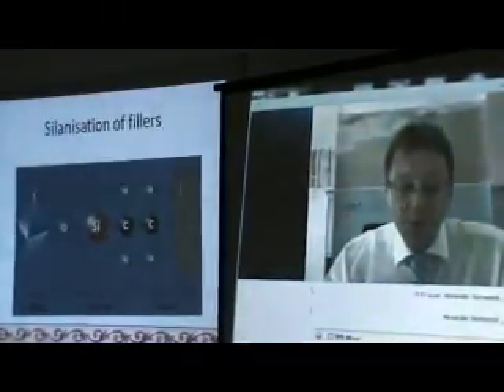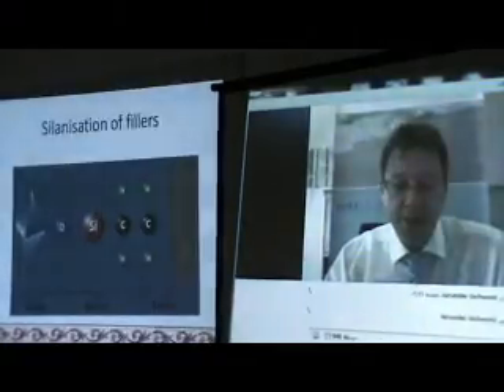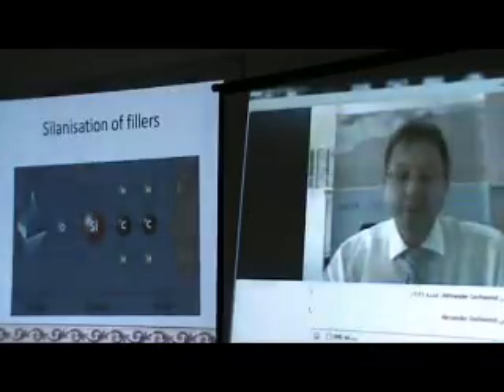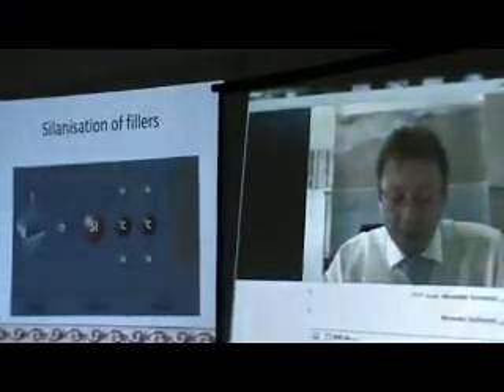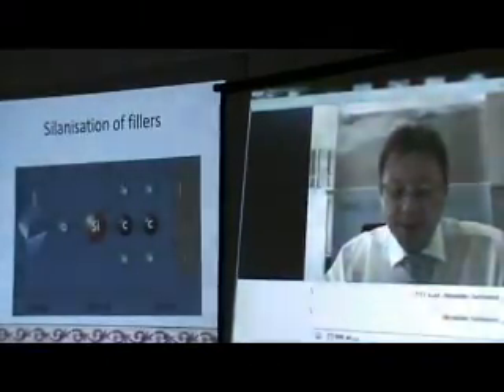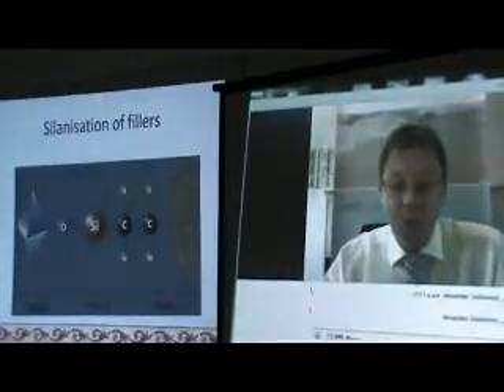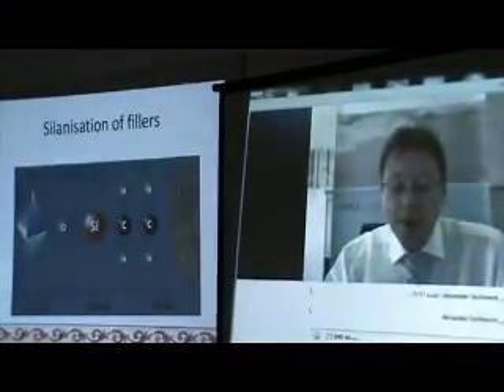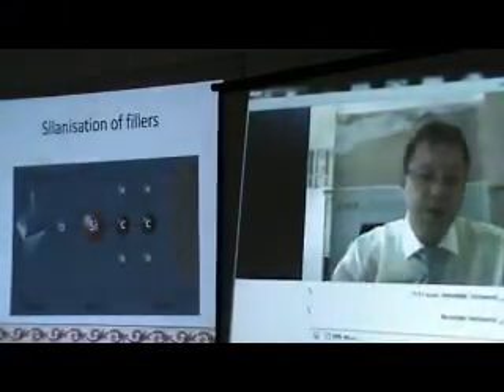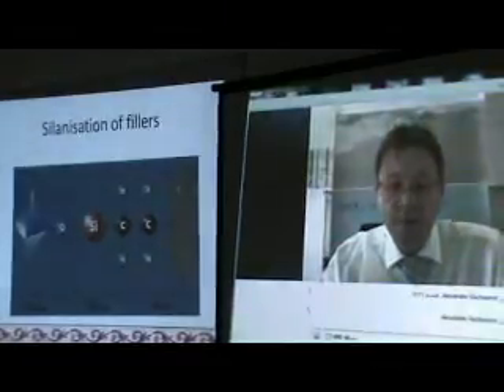On slide number 18, you see this chemical process of silanization. On the left side, you see the glass filler, which has an oxygen molecule, and then you see the silane, which has on one side a part which can connect to an oxygen molecule, and on the other side it has a carbon molecule. Now, the carbon molecule will connect to the resin, and the oxygen molecule will connect to the glass particle. So it's very important to have a good quality of the silanization.